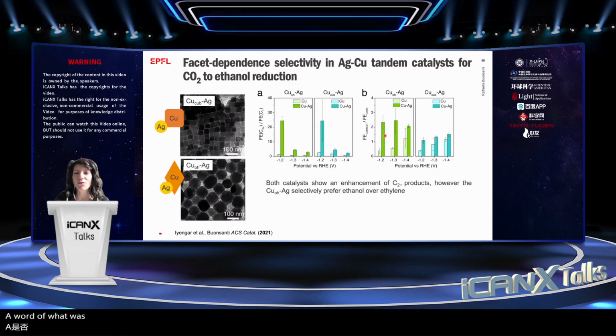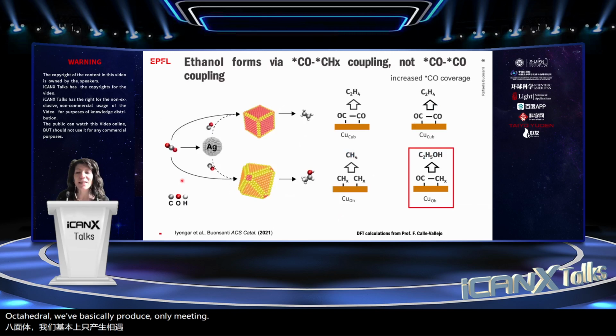However, what was interesting to find is that the copper octahedra were selectively preferring ethanol over ethylene. And this was quite a surprise because, as I mentioned before, copper octahedra will basically produce only methane. And here is where we performed some DFT calculations in collaboration with Professor Federico Calle-Vallejo. And these calculations showed us that the formation pathway for ethanol proceeds via CH-CO coupling, so it's distinguished compared to ethylene.